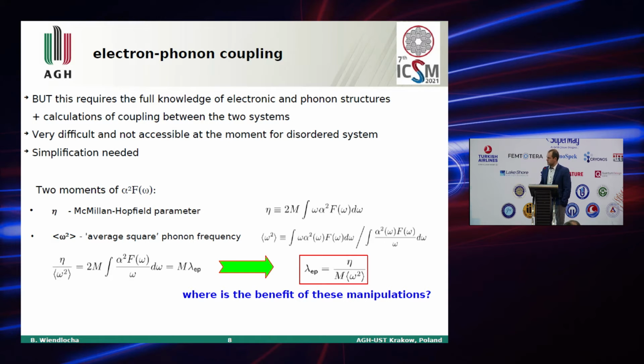So first it's the McMillan-Hopfield parameter, which is an integral of the Eliashberg function multiplied by omega. And the second is the so-called average square phonon frequency, but this is not exactly the average square, this is just the name used in literature, and this parameter is also defined using the Eliashberg function, using the ratio of two integrals.